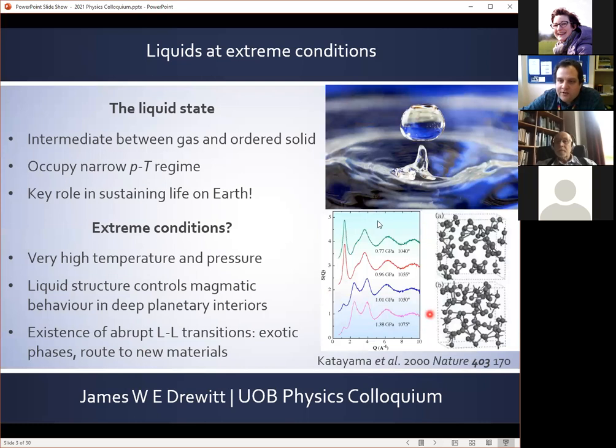An example of this is liquid phosphorus, which is perhaps one of the few convincing materials which has been shown to undergo a liquid-liquid transition. So here's the structure factor measured for liquid phosphorus, and there's a distinct change in structure over a very abrupt pressure range at elevated pressure, where the liquid structure changes from a molecular liquid insulator to a metallic network structure.